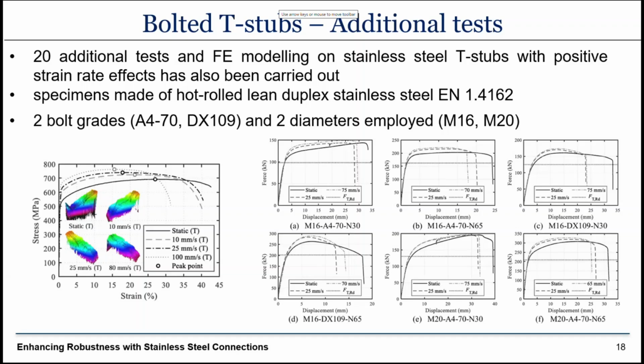Now, having seen that the stainless steel has a negative strain rate effect for small strain rates, we talked with Southampton, who at that time had some additional specimens made of lean duplex stainless steel grade from another project, and we said, why not test that as well? So they did, on top of our test, some additional tests on T-stubs made of lean duplex stainless steel grade 1.4162 at high strain rates, and in that case, the material has the expected strain rate effect, so increasing ultimate stress with increasing strain rate.